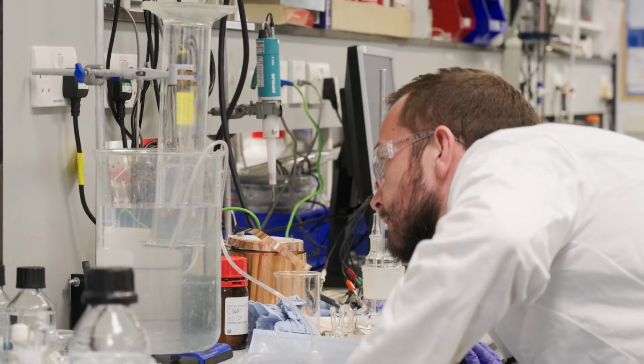So what that means is when your carbon dioxide gas gets trapped in there, it doesn't form bubbles, it gets trapped in very high concentrations, and that means that you can get a fast rate of reaction at the catalyst surface. So it's kind of artificially giving you a very high level of carbon dioxide, which then gives you a very high rate of reaction.